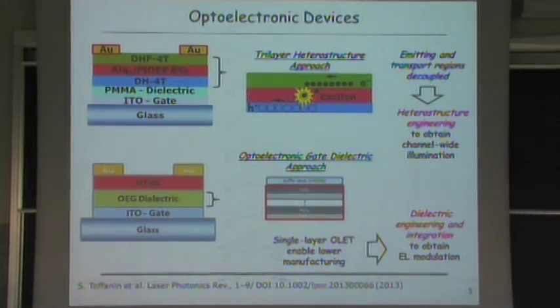I show here the optoelectronic devices we used. The first one is an OLED tri-layer heterostructure, where you can see the emitting and transport regions decoupled. So we worked on the heterostructure engineering in order to obtain channel-wide illumination. The second one is an DH4T-based device. It's a single layer device, so we can build many of them in order to try to integrate a new optoelectronic gate dielectric fabricated by the Politecnico of Milano by pulsed laser deposition instead of the standard PMMA dielectric layer.